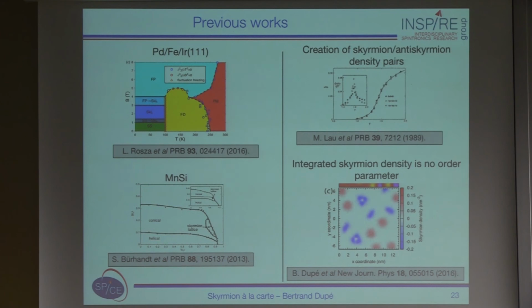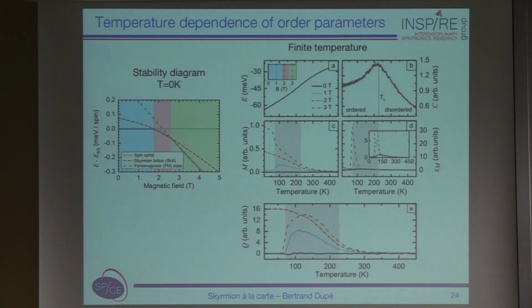So we cannot analyze the phase diagram with this quantity. So what we did is use Monte Carlo simulation adapted for spin glass behavior. Namely, we did parallel tempering Monte Carlo in order to obtain order parameters with which we could characterize all the phases. Here is a reminder of the 0 Kelvin phase diagram for palladium iron iridium. You start with the spin spiral ground state, that is what we expect. Then you increase the magnetic field, you go into a skyrmion lattice, and then you go into a ferromagnetic state.